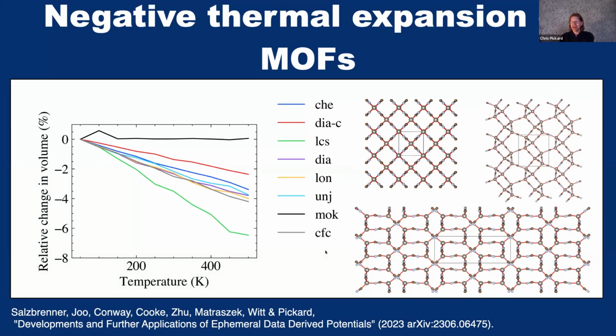He was able to find the MOF structures, well, the ones that were known or discussed in the literature. And of course, in these searches, we get loads of other ones as well. But then he went one step further in that he calculated the negative thermal expansion of these MOFs. For the ground state of the interesting MOFs that he came up with, he was able to do a large unit cell molecular dynamics run, vary the temperature, and just observe how the lattice parameters changed. So a very easy way of evaluating the negative thermal expansion.